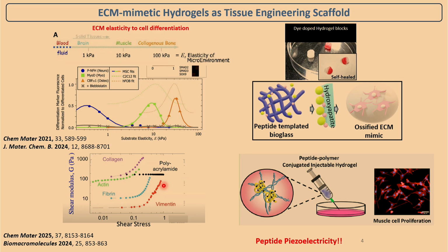But if you really go for cardiac muscle cells, it has to have that actuating behavior. If such cardiac tissues, or our veins and arteries, had shear thinning hydrogel-like behavior, what would happen? During systole-diastole movement, you could not withstand the pressure. It would fall and you would die, right? So for that, what you need is strain stiffening. It should have a counterintuitive behavior: you put force, but it resists. As a result, you can see that at very low strain, the shear modulus increases.